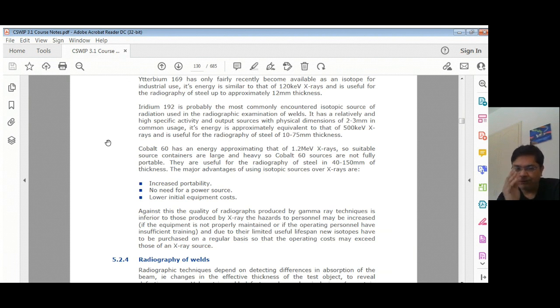So you can imagine from iridium 192 to cobalt 60 how the jump is almost 2 times the X-ray source. So suitable source containers are large and heavy. So cobalt 60 sources are not fully portable. They are used in industrial radiography up to 150 mm thickness. The major advantage of isotopes over X-rays is increased portability. I said you can take it easily outside. Very tough for the environment, and no power source is required, whereas X-ray is a power guzzler. Gamma ray is zero power. So lower initial equipment cost also. Gamma rays are very inexpensive.